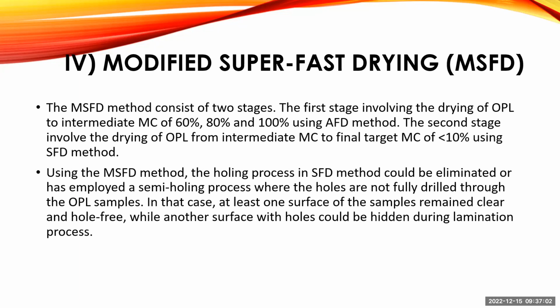By using this modified super fast drying method, the holing process in the super fast drying method could be eliminated, or has employed a semi-holing process where the holes are not fully drilled through the oil palm lumber sample. So at least one surface of the sample remains clear and hole free, and the other surface with holes could be hidden during the lamination process.